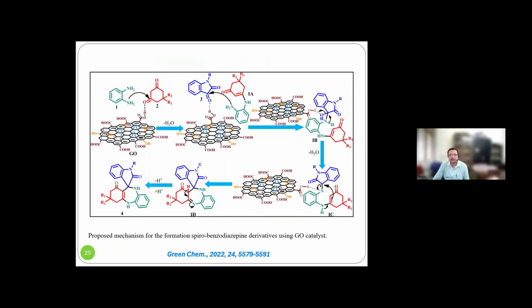So then this is the probable mechanism. Again the acid functional group of the graphene activates the carbonyl carbon. Then imine formation. After that intramolecular addition, and tautomerization gives the spirobenzodiazepine molecule.